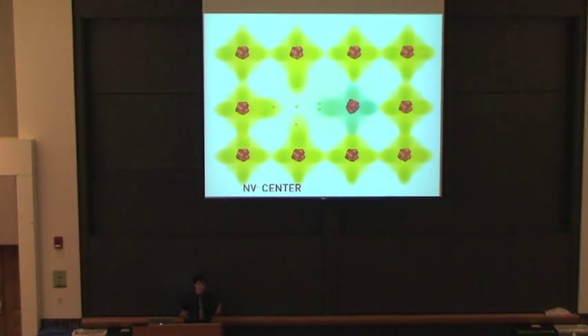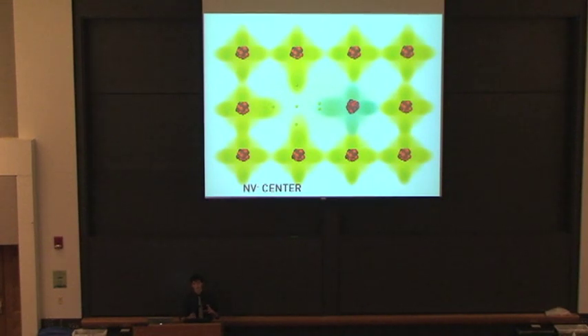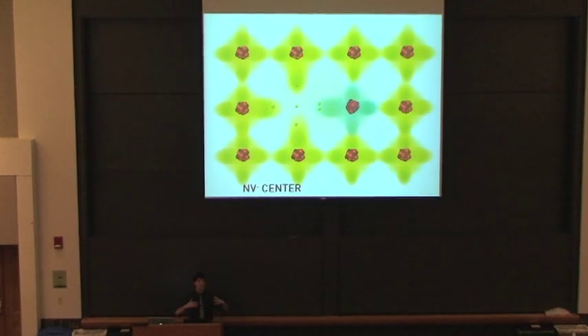We then heat up the diamond, we anneal it, and these gaps in the lattice naturally will gravitate towards nitrogen impurities in the diamond because the lone pair of the nitrogen is looking for space, so it's entropically favorable for the two to couple.